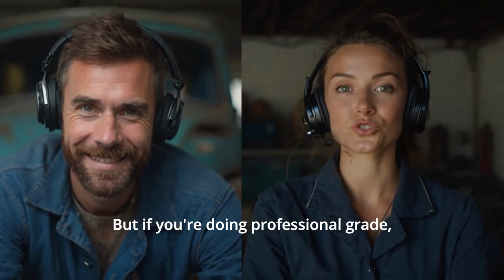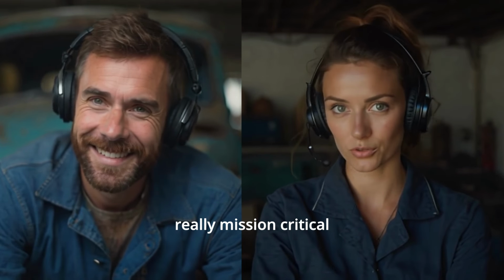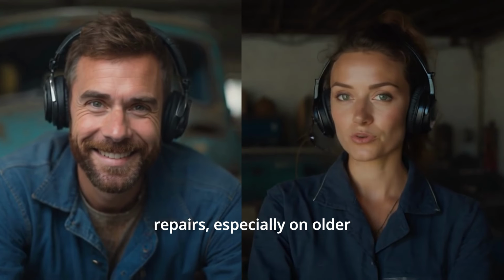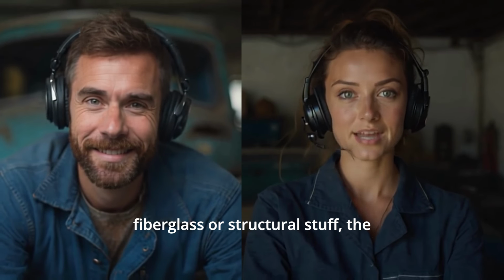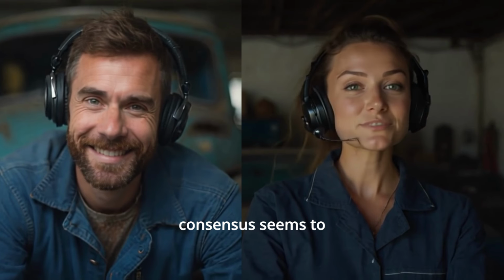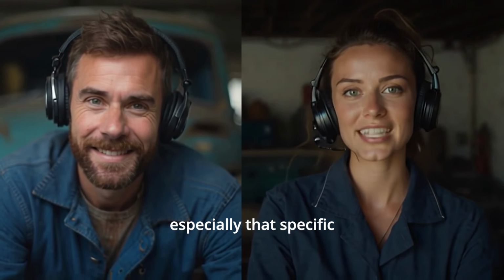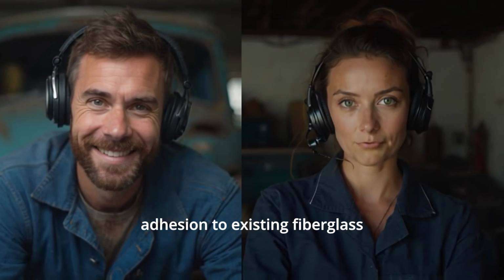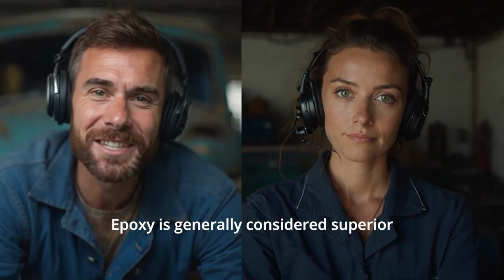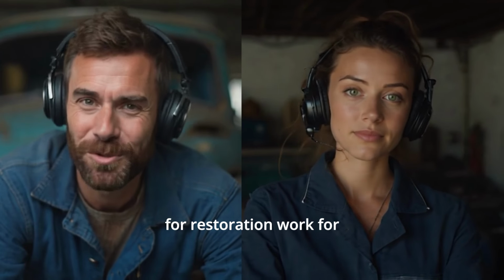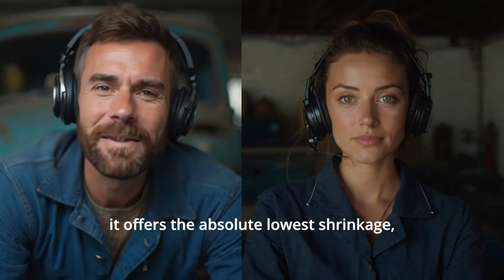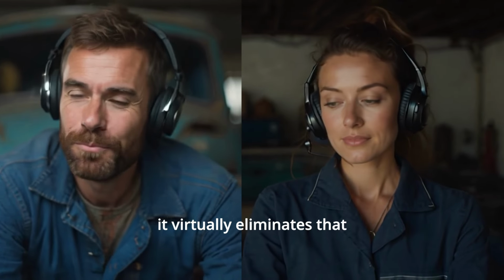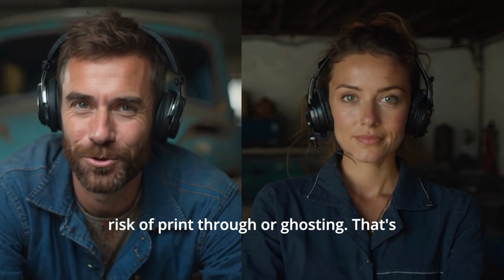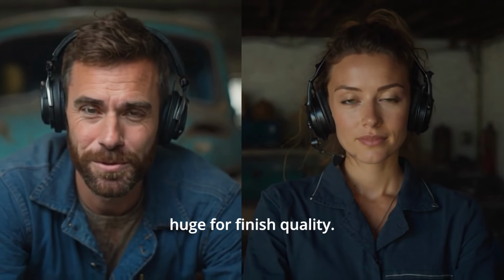But if you're doing professional grade, really mission-critical repairs, especially on older fiberglass or structural stuff, the consensus seems to point squarely toward epoxy. Why? What makes it the top tier, especially that specific adhesion to existing fiberglass you mentioned? Epoxy is generally considered superior for restoration work for two main reasons. First, it offers the absolute lowest shrinkage, usually less than 1%, so it virtually eliminates that risk of print-through or ghosting. That's huge for finish quality.